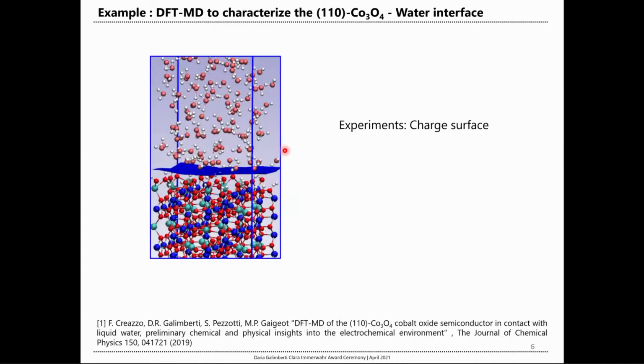The second example that I want to show you is the cobalt oxide water interface. Cobalt oxide has been proposed as a possible interesting material for water splitting, and in particular for the oxygen evolution reaction. In particular, this cobalt phase of the cobalt oxide, the 110 surface, if you look at it experimentally, you will see that it's a charged surface. Depending a little on the cut, since it's a double layer material, you can have a positive surface or a negative surface, but it's for sure a charged one. And when you put this surface in contact with water, it will rearrange, it will reconstruct, and simulation can tell us how. But more interesting is that if you look at this surface and say it's charged, what you would expect is, okay, water will rearrange following the field generated by the surface.